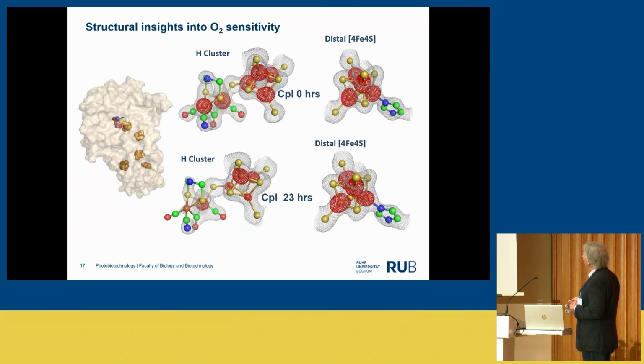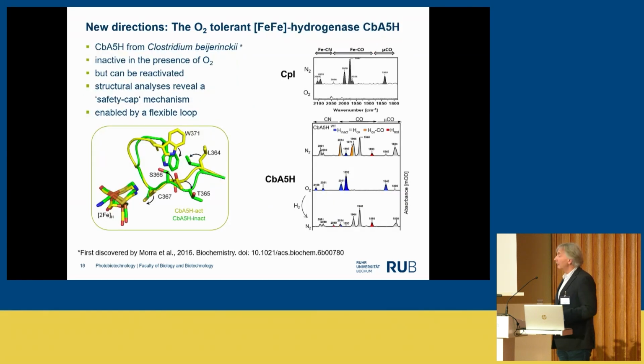After incubation of 23 hours, in the control, you still have the full cluster, but you see in the H cluster, you lose the density, meaning the cluster is degraded. So this is a clear hint. If you put the enzyme into oxygen, the enzyme is degraded because the cluster is not there anymore. Okay? What is the solution? You can look in nature. Okay? You can look in nature if you find an oxygen-tolerant hydrogenase.